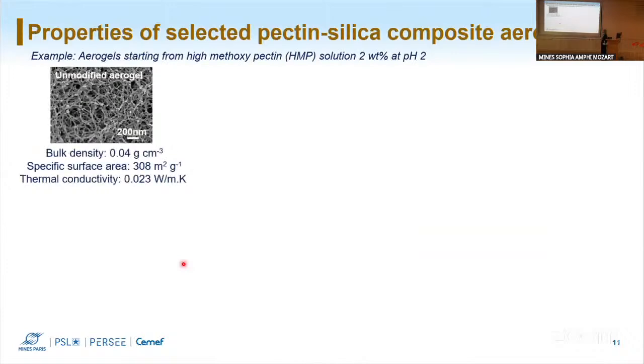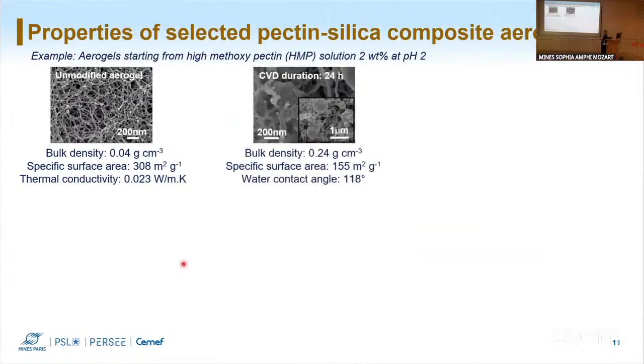Now, I will give you an example for one formulation starting from a high methoxyl pectin solution of 2 wt% at pH 2. These are the properties of the neat material. We see low density, high specific area, and low thermal conductivity. And after 24 hours of chemical vapor deposition, we see that we have a huge increase in bulk density and a decrease in surface area. However, we get hydrophobic materials, which was our goal.